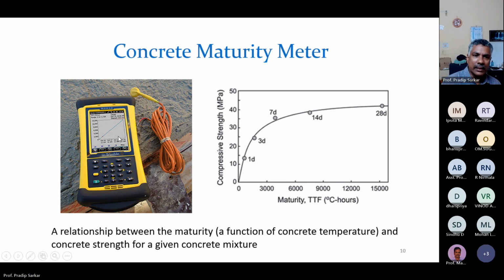What maturity does, you have to take this instrument to the site. It calculates, again from the surface, the heat of hydration, and maturity is a function of concrete temperature, right? Maturity is a function of concrete temperature and time, and this time-temperature function is related to the compressive strength in this maturity method. So using this instrument, you will go to the site and get the maturity, that is the temperature-time history. From the temperature-time history, concrete strengths are correlated. So this is also not an automated system. You require human intervention. One person has to go there and get the data and find out.